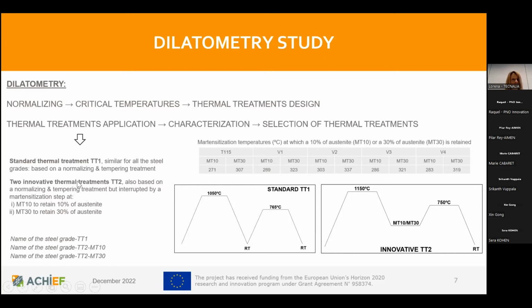The thermal treatments applied are 3. The standard one, which is similar for all the steel grades and is based on normalizing and tempering, and then 2 innovative thermal treatments, TT2, that are also based on normalizing and tempering treatment, but interrupted with a martensitization step in between. This martensitization step can take place at MT10 temperature to retain 10% of austenite, or at MT30 temperature to retain 30% of austenite.